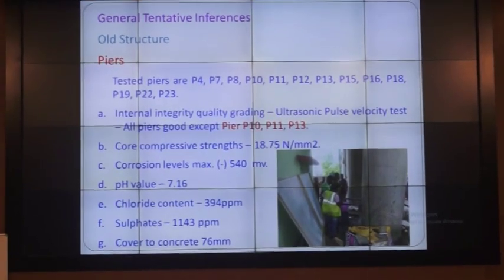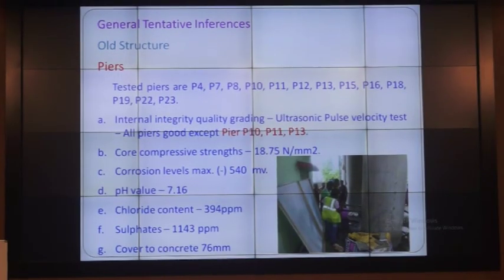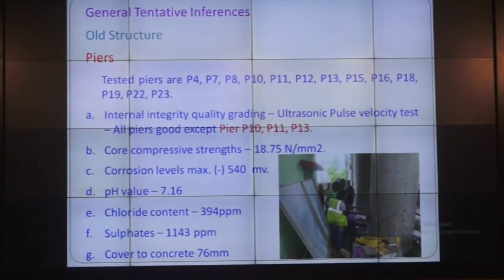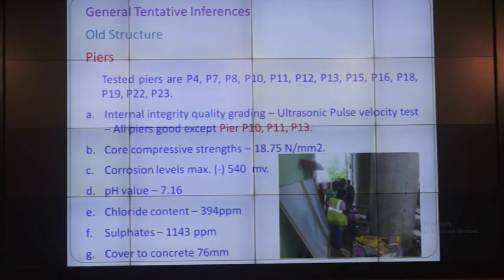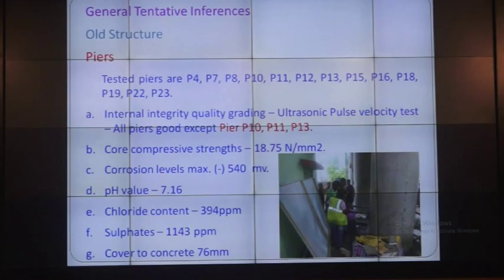That old structure was built about 20 years back, 18 years it was shown there, 20 years back. Tested piers are P4 to P23. Integrity quality grading, ultrasonic pulse velocity test, all piers good except 10, 11, 13. Core compressive strength obtained. Please note, these are the results we obtained from the site after sampling, either the ultrasonic or the cores. Core compressive strength is only 18.75 Newton per square mm. That is 18.75 MPa.